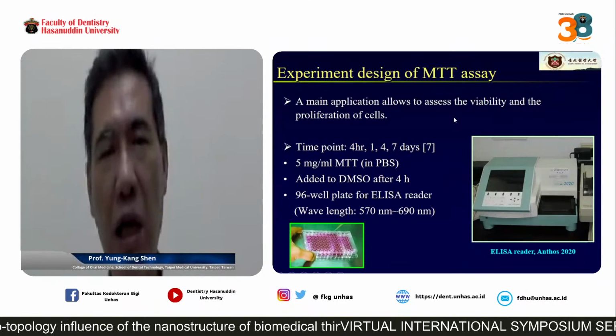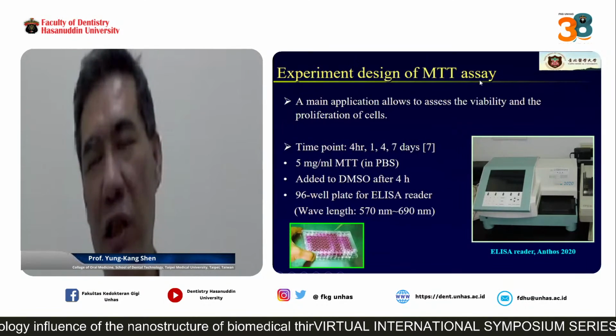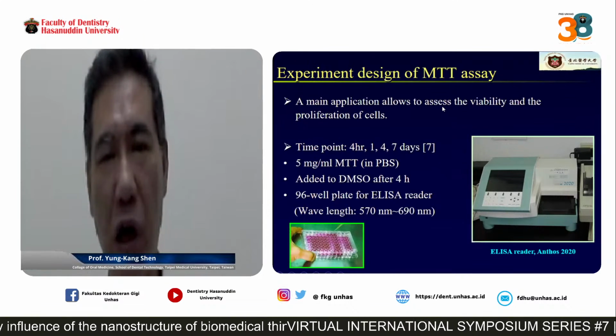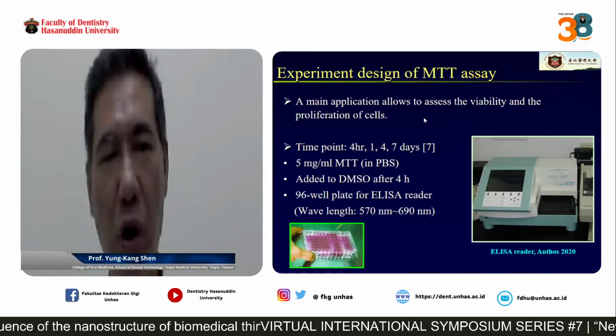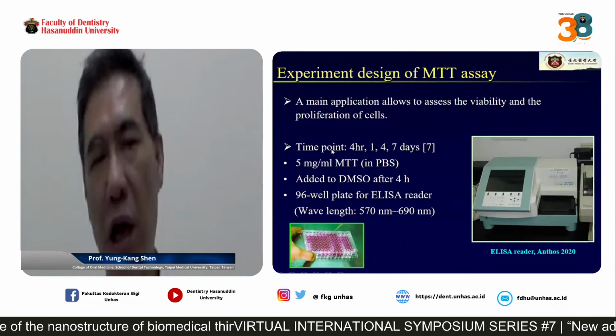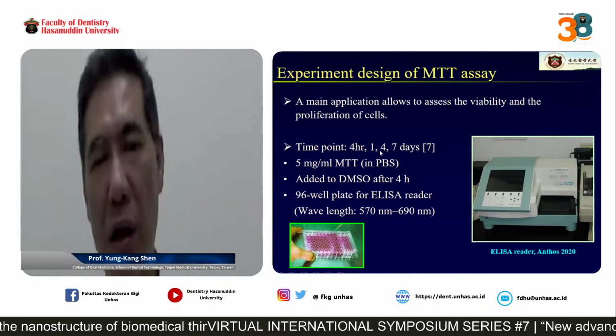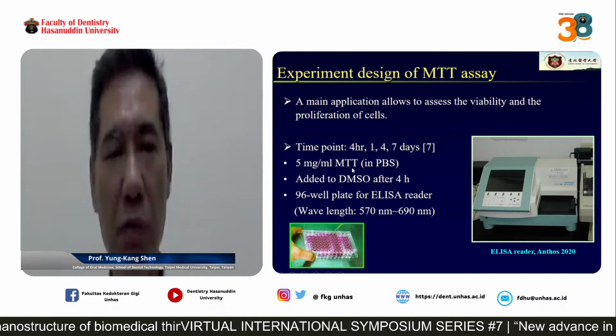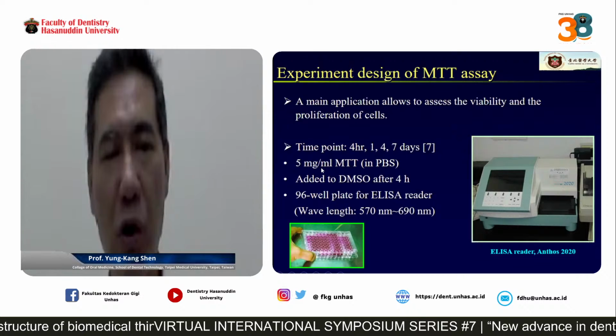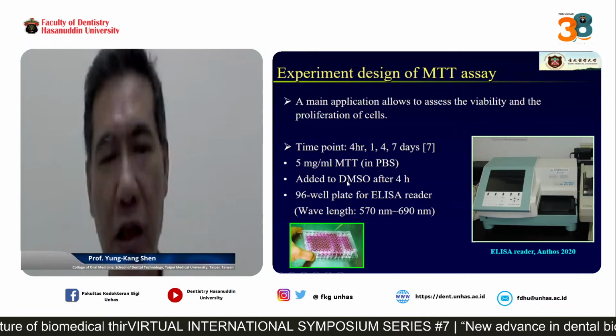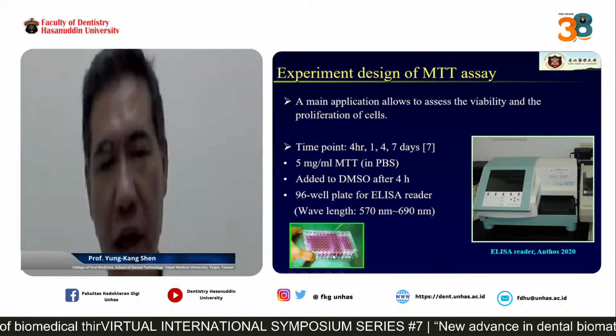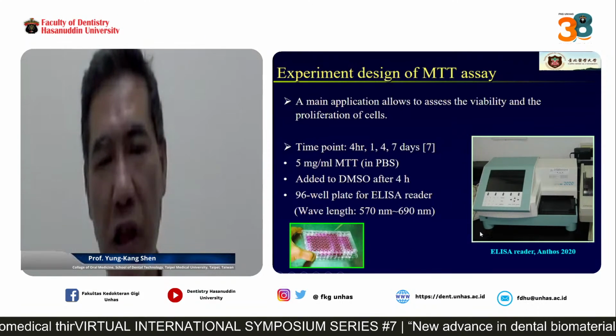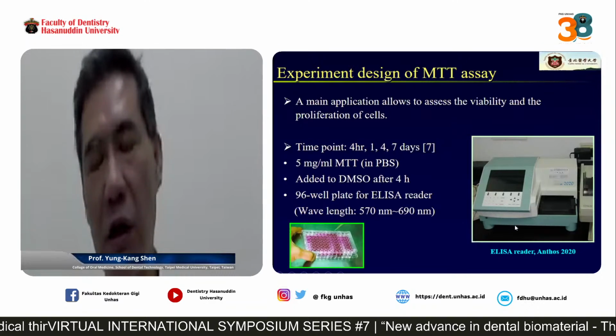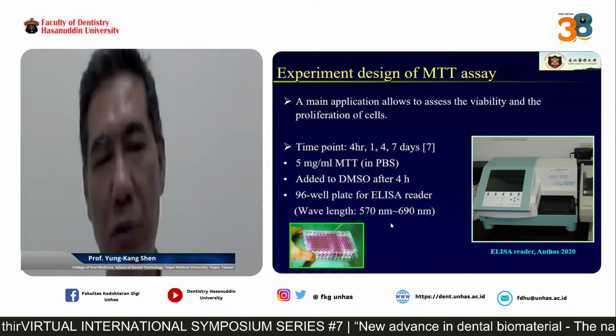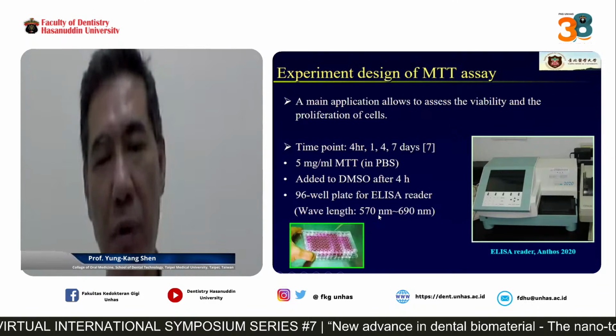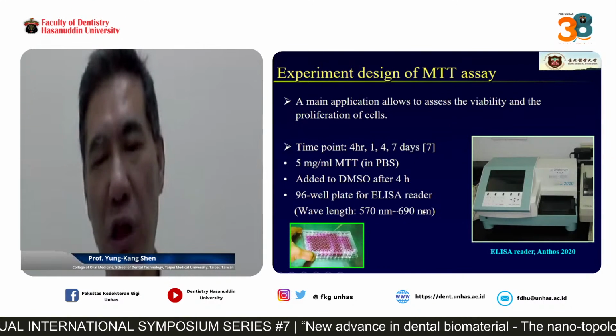And for cell culture, first we use the MTT assay to see the cell numbers. The main application is to assess the viability and proliferation of cells. For time points, we watch the cells for 4 hours, 1 day, 4 days, and 7 days. In MTT, in PBS, we use 5 microgram per microliter, added to the DMSO after 4 hours. We use a 96 well plate for the ELISA reader. This is the ELISA reader to observe the cell numbers, at wavelengths between 570 nanometer and 690 nanometer.